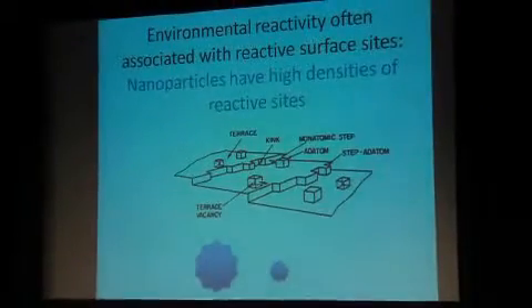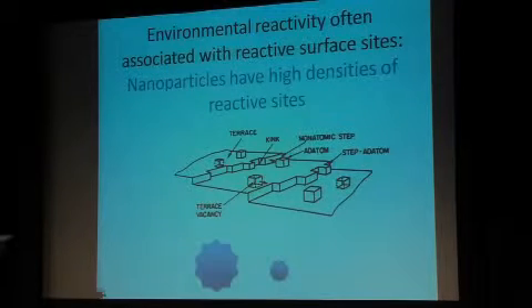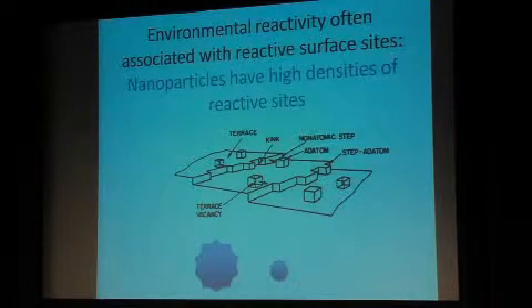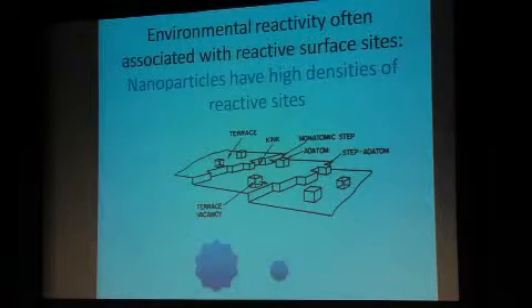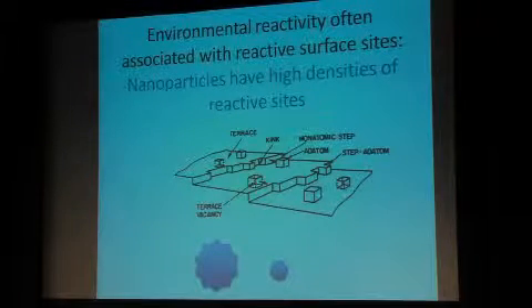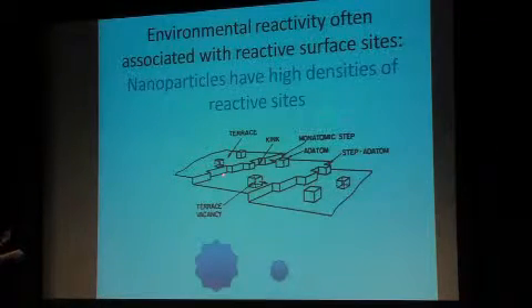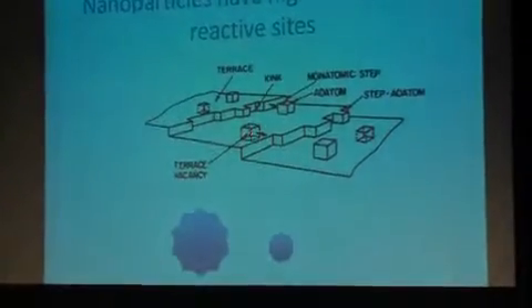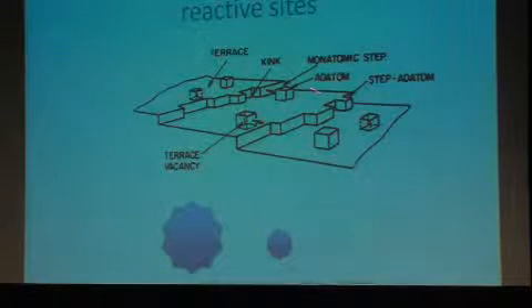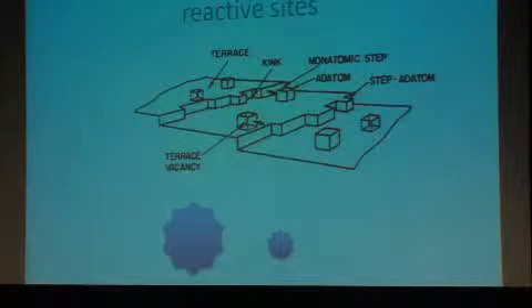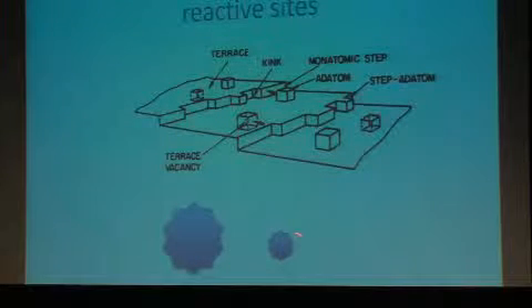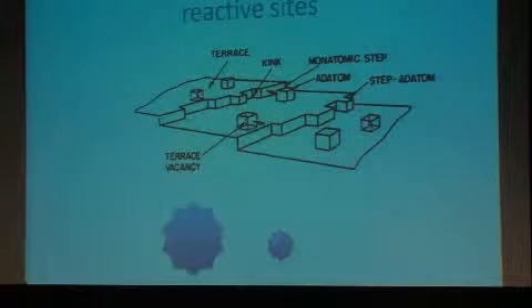Environmental reactivity of surfaces, I'm going to say of minerals, but of other things as well if they're solids. A lot of times how they react is not based on how much total surface you have, but the density of certain reactive surface sites. So very typically, for example, let's say that this is a flat, perfect mineral, but it's got little steps on it that are maybe monatomic steps or something like that. And then it may have a kink. It may have a vacancy, which would be a hole down in there. It may have an adatom. These are the things that often are controlling how it adsorbs a toxic organic or a toxic metal. Okay? And when you get down to very small particles, the density, and this is kind of a bad schematic, the density of those reactive sites really increases.